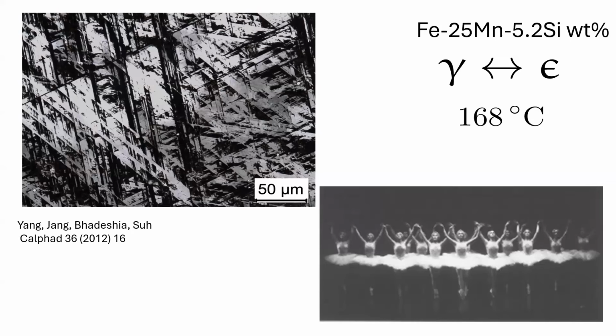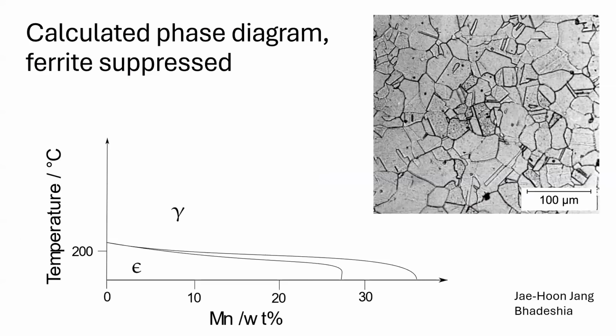So this is the structure. And no one in the whole world has produced hexagonal iron without this mechanism. So there is no possibility of atoms diffusing any distance at 200 degrees centigrade in iron. So we cannot actually make structures which look like this, which are coarse and crystals of equal size, roughly. No one has ever produced hexagonal iron by a mechanism which requires diffusion. Of course, in the center of the Earth, the story is different. You've got 10 to the 23 kilograms of hexagonal iron in the middle because the pressure there is incredible.